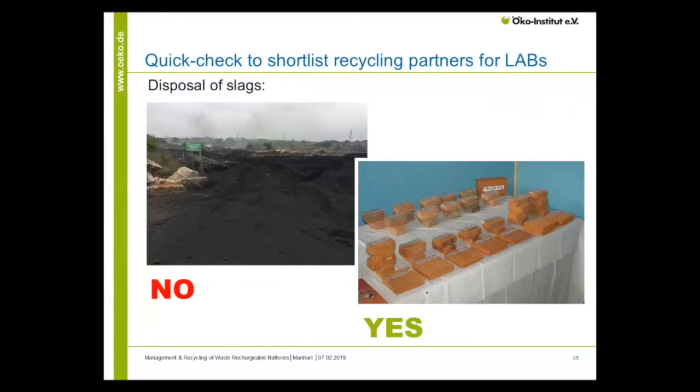It's extremely difficult to detect whether this is soil or slag. So every responsible smelter needs to provide a sound solution for the slags. And there are good measures. When you tune your process to reduce the lead content in the slag, you can use it for tile or brick manufacturing. You make a commodity out of it, which is acceptable for several uses, outdoor uses, for example, or uses in places with non-permanent residents. So slag management is a very important aspect of responsible lead smelters.